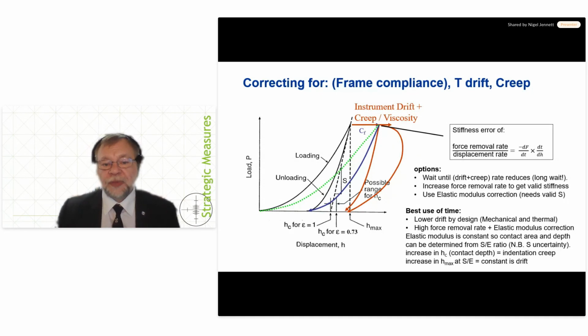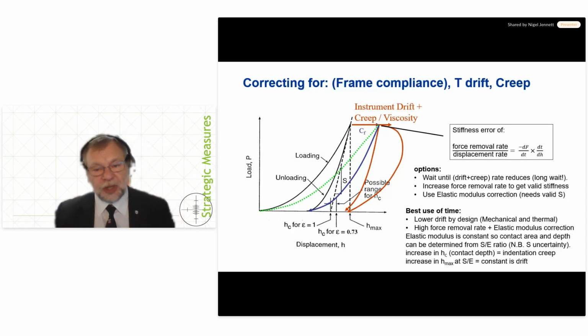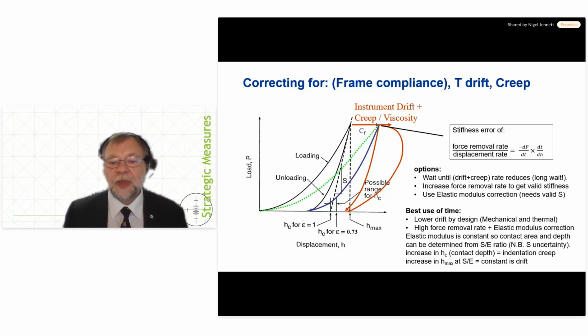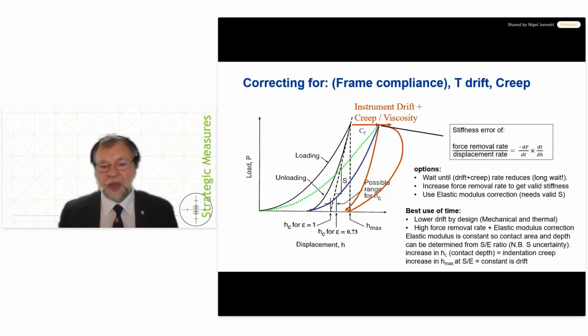because the faster you unload, the less error in absolute drift you get, whether it's drift or creep. Then you've got elastic modulus correction, which says, well, if I know the elastic modulus, and we know that it doesn't really change that much with creep or thermal drift, then I can reverse the equation, in fact, and get out the size of the indentation that must be there for the stiffness as I measure it to give me the correct elastic modulus. And therefore, I can use elastic modulus correction as a way of tracking the actual increase in the contact size, and I can compare that with the actual change in the displacement rate and start to separate the drift from the creep in my indentation experiment.